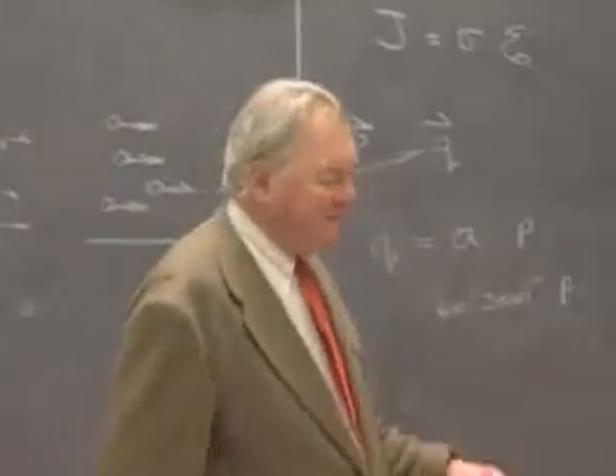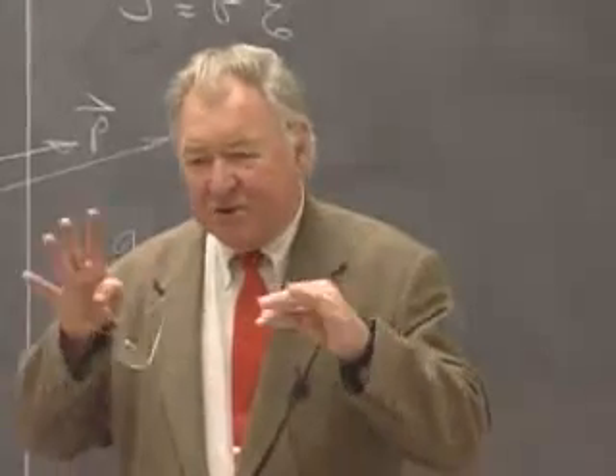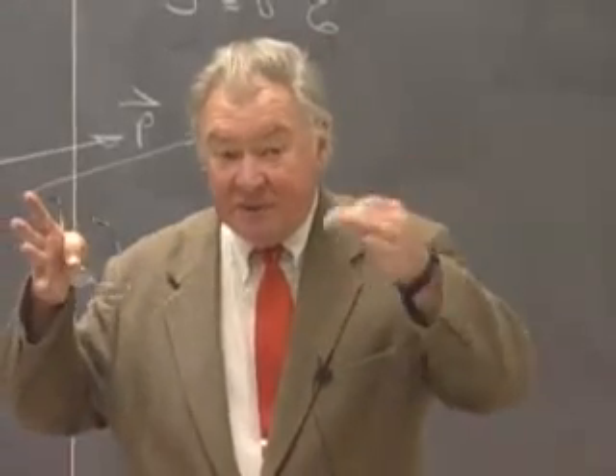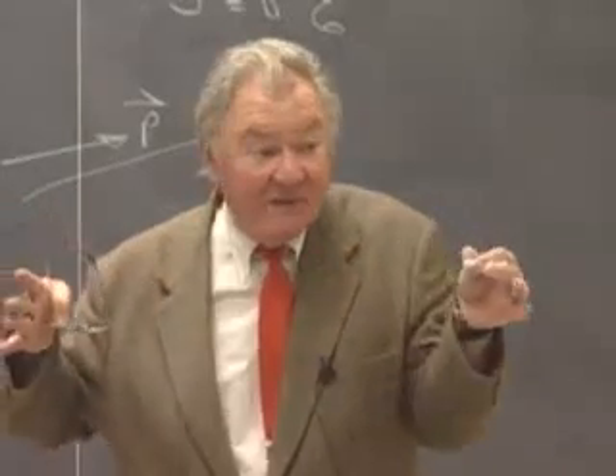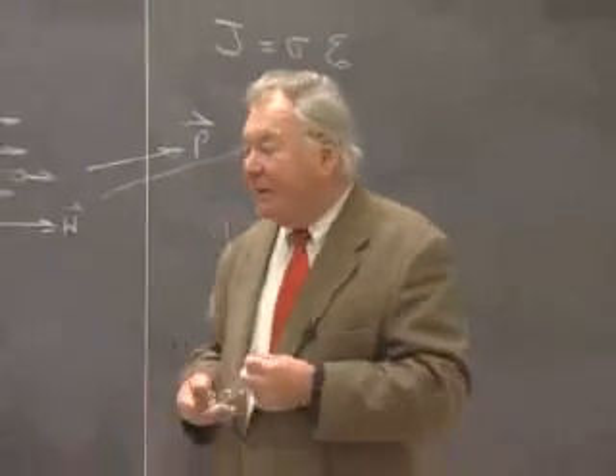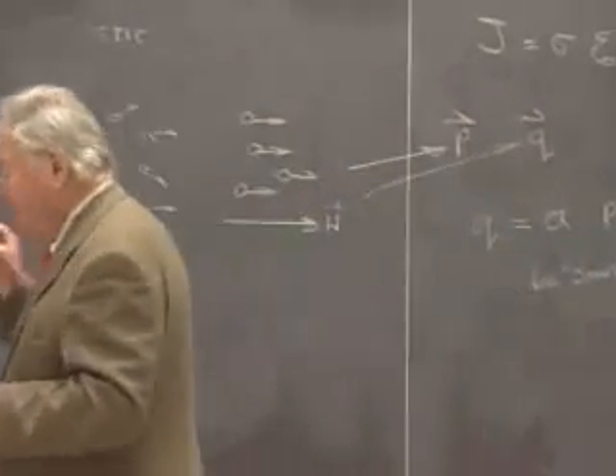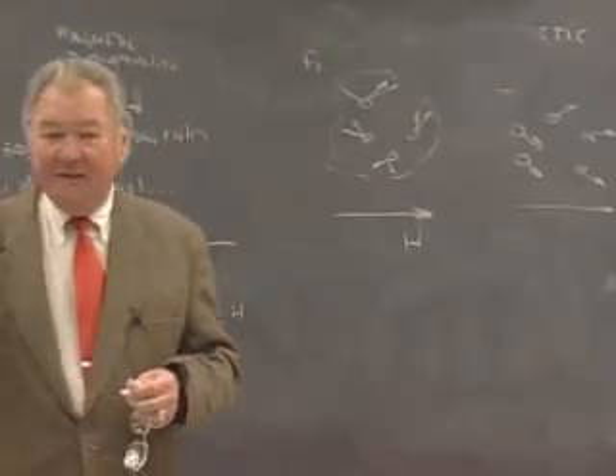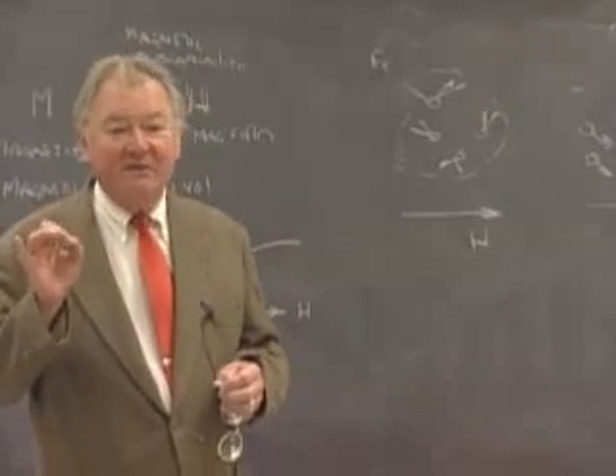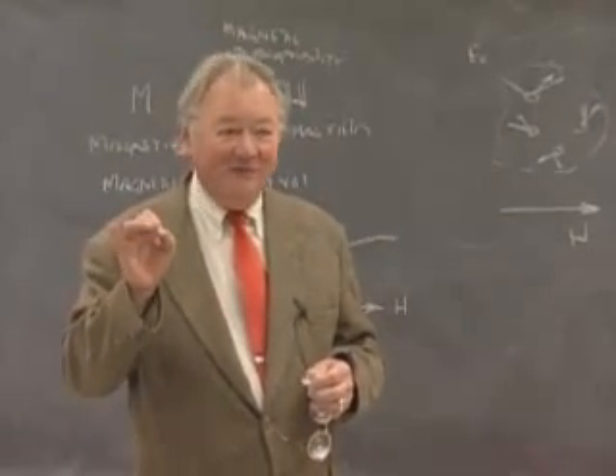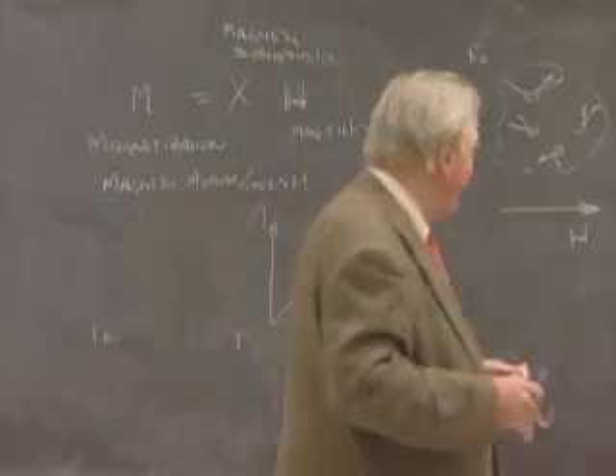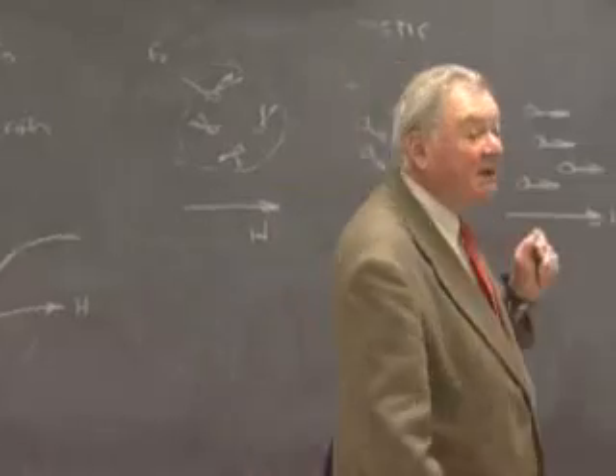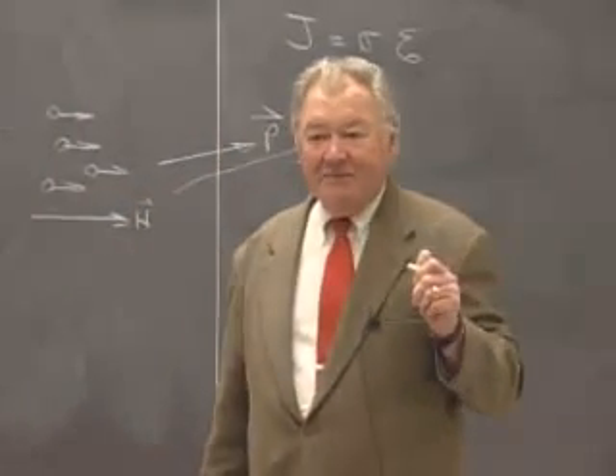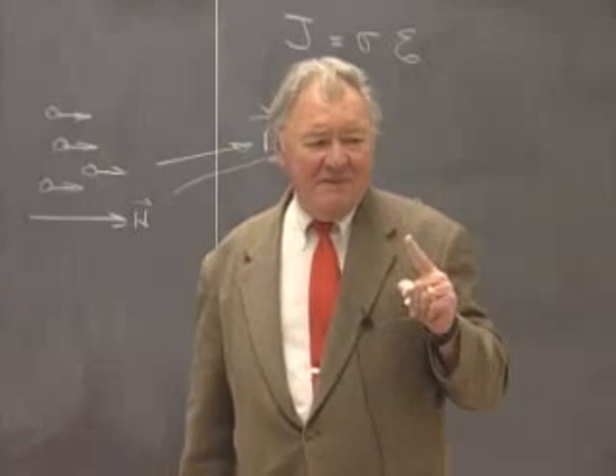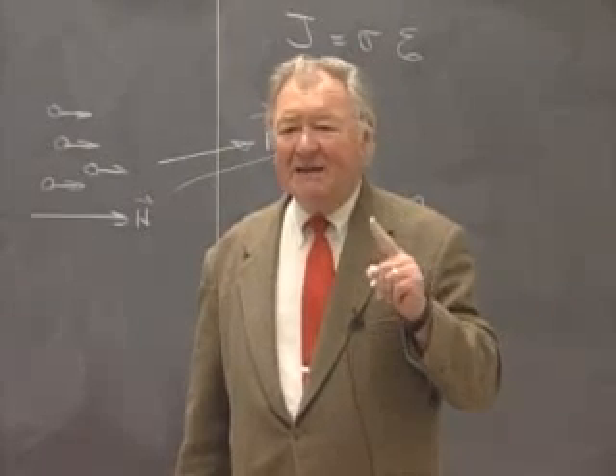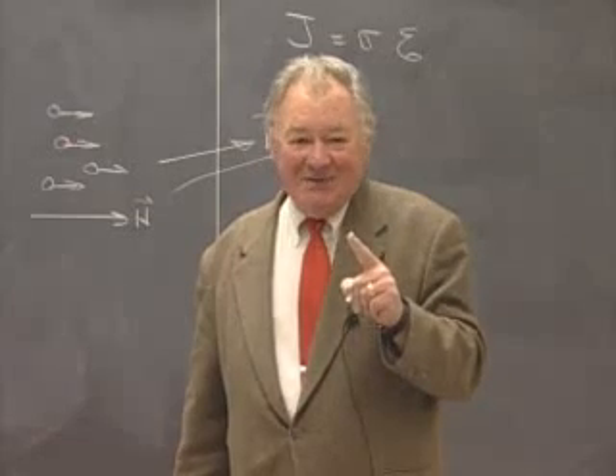For ordering to occur, temperature and applied field go hand in hand. Increased temperature tends to create more disorder. Increased magnetic field tends to align the moments. And in the days when MIT had a national magnet laboratory, the magnet laboratory held the record for the strongest magnetic field ever produced artificially by man. And if you took that magnetic field and applied it to the system of dilute iron in a glass, you would have to lower the temperature of the sample to about 3 Kelvin before you would begin to see saturation.